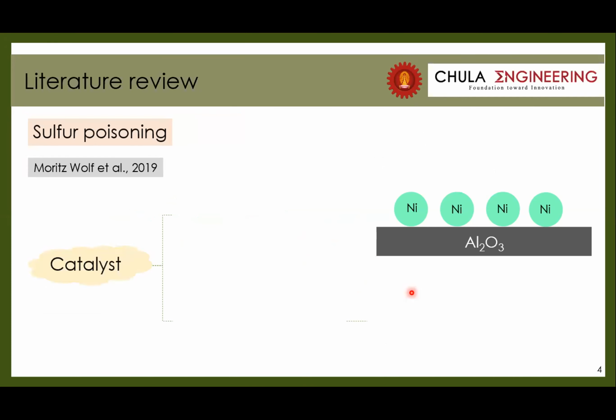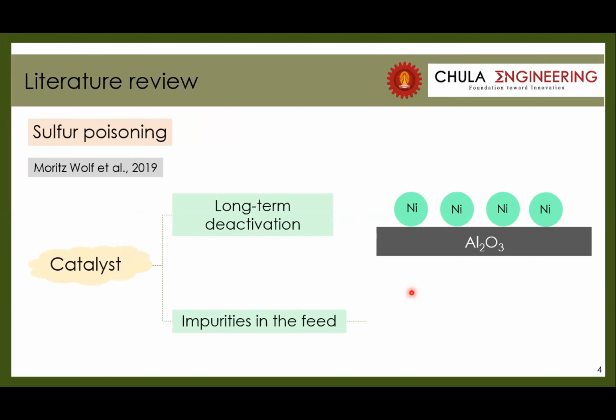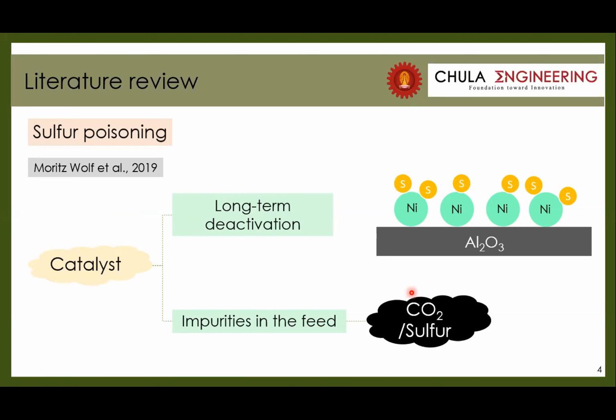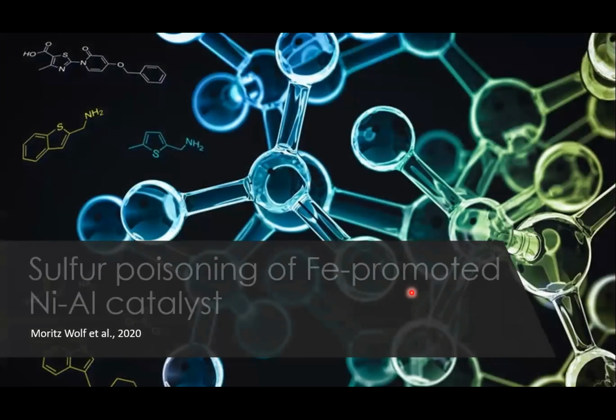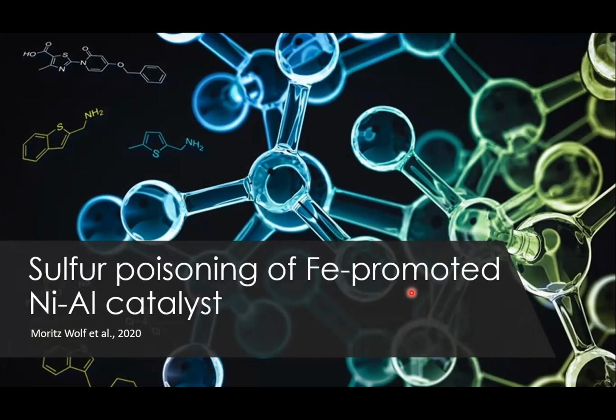Sulfur poisoning. Moritz Wolf et al. said that the catalyst is stressed not only by long-term deactivation, but also by impurities in the feed, which uses carbon dioxide separated from industrial exhaust gas. It contains some sulfur, and sulfur is a very quick and irreversible poison on nickel catalysts. Sulfur poisoning of iron promoted nickel aluminum catalyst. This is the data obtained from Moritz Wolf et al.